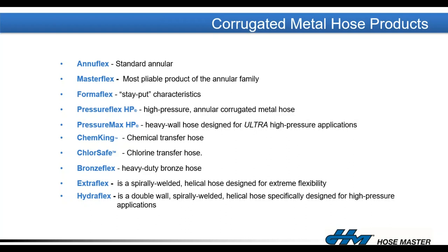If you need a more flexible hose, either because the hose is going to be bent more tightly or because it's going to be cycling more frequently, then we take that Annuflex and basically compress it using a special operation to form our Masterflex. And by increasing the number of corrugations per foot of hose, that Masterflex is able to be bent more tightly or undergo a higher cycle life because you have more corrugations per foot to help enhance that flexibility and cycle life of that hose.